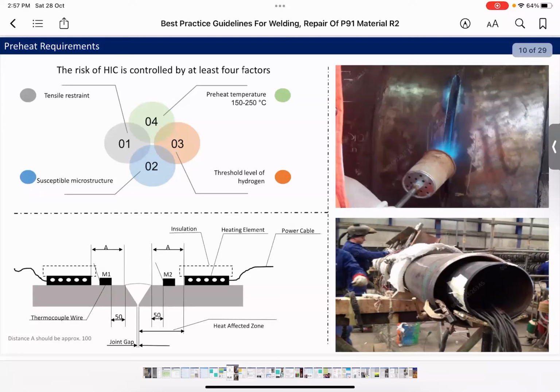This hydrogen can be picked up from the liquids on the pipe, or the moisture in the atmosphere, or the filler material that can have hydrogen. So for these things, we should use low hydrogen designation electrodes, and we should keep our preheat temperature between 150 to 250. I would like to bring your attention here to a very important point, that preheat by torch is not allowed. It cannot control the preheat temperature.